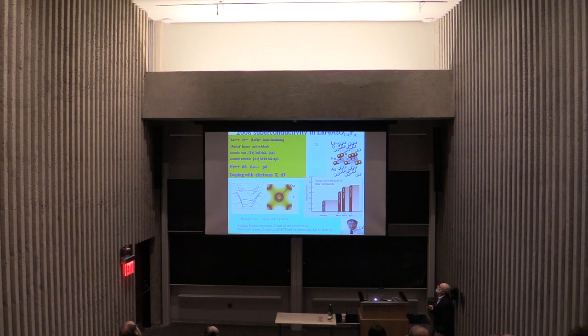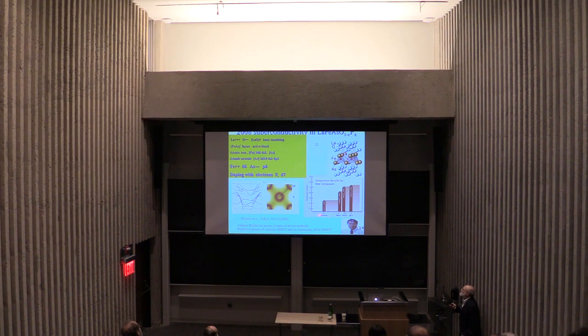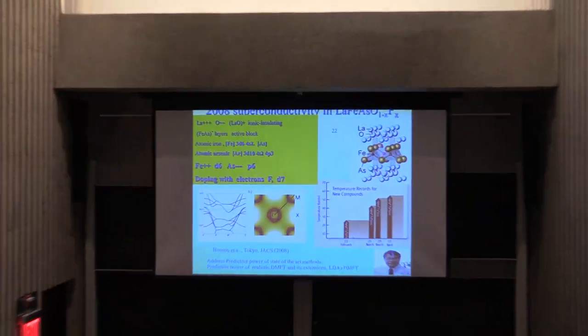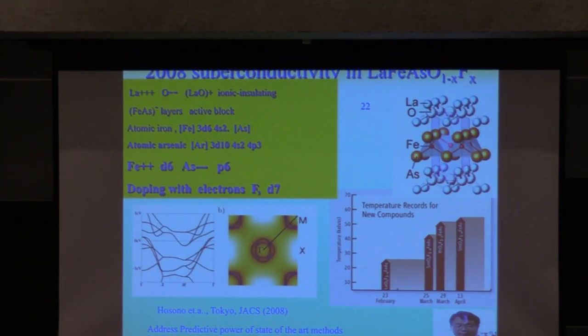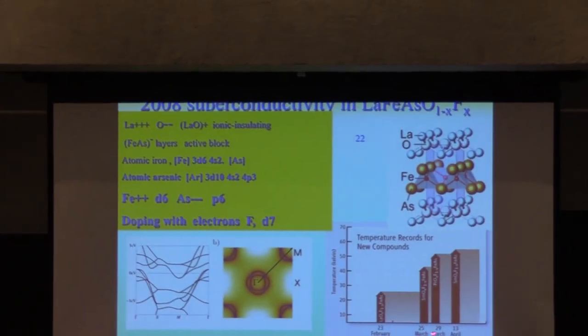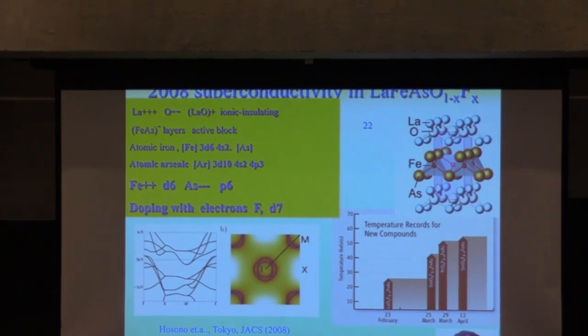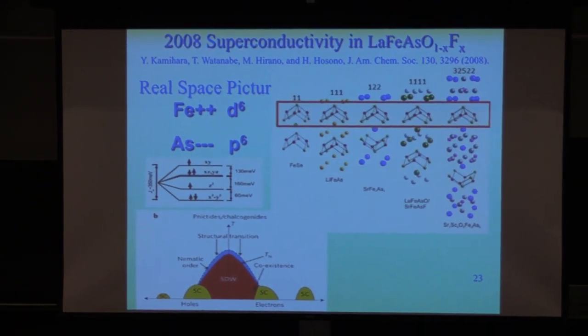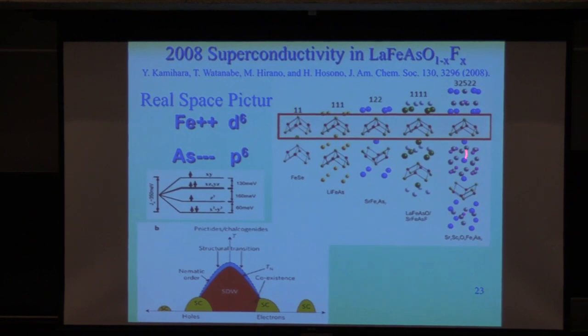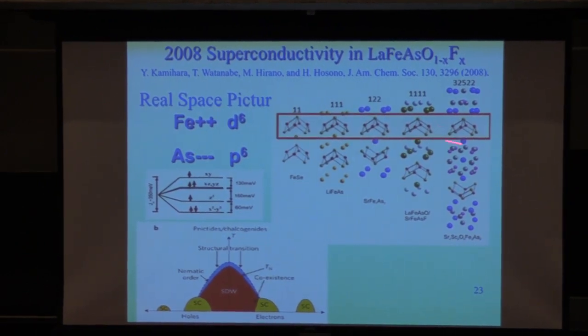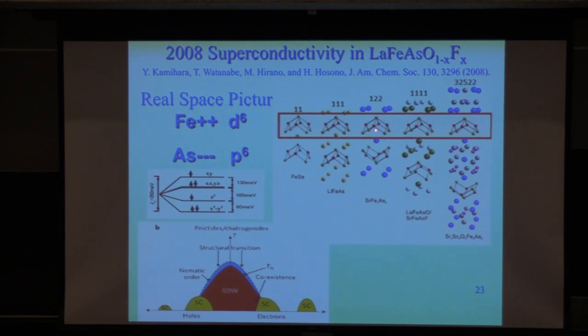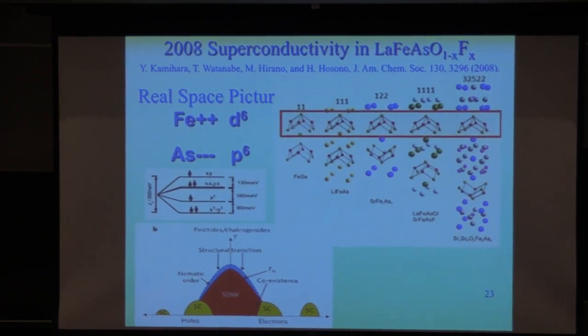Because the iron pnictides, these materials that were discovered recently, were the first time really that we were able to test our methods in real time, in the sense that something new comes and finally we have some method for guiding ourselves in what's going on. So I'll just give you some highlights of what we were able to do. The material was discovered experimentally by this fellow, and now there are many, many materials which have the same structure, the same pattern, these iron pnictide layers, but they have many, many different interlayer things.